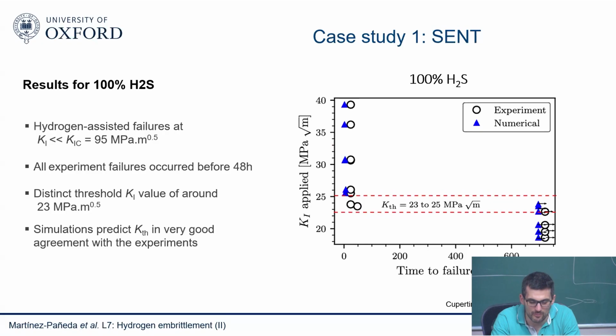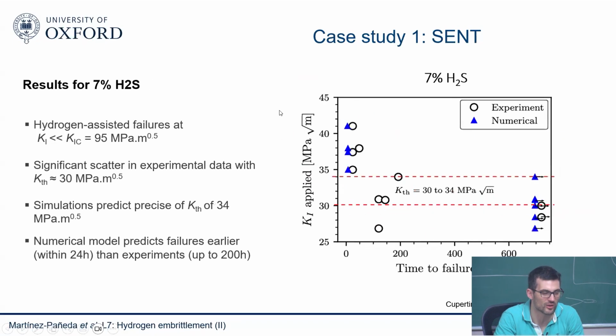But at the same time, it's a bit of a challenge to do that, because you can see this one failed very soon, but this one didn't fail. And the change in load is very, very small. So the industry is worried. What if I had waited a bit more, maybe this one will fail? So they don't really know what's happening. The good thing is that our numerics seem to be in good agreement with experiments. So that's a good indication. So now we can interrogate the numerics.